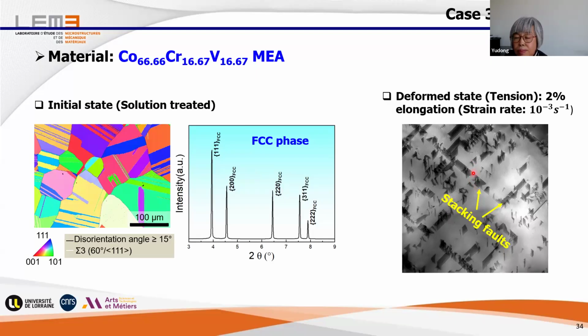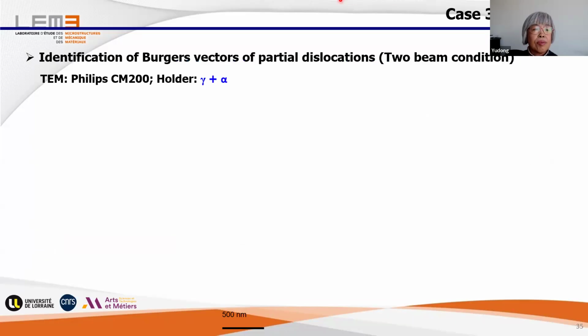We deform this material at room temperature with this strain rate and to 2% elongation. And you see, as this ultra low stacking fault energy material deforms, we form not perfect dislocations, but extended dislocations. You see, with stacking faults, these are the stacking fault fringes, bordered by partial dislocations. This configuration is called extended dislocation. And then in this application, I will show you how to identify the Burgers vectors of partial dislocations.